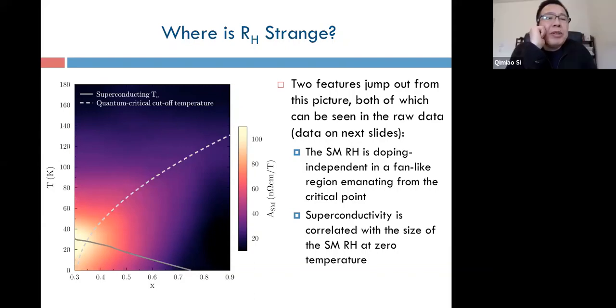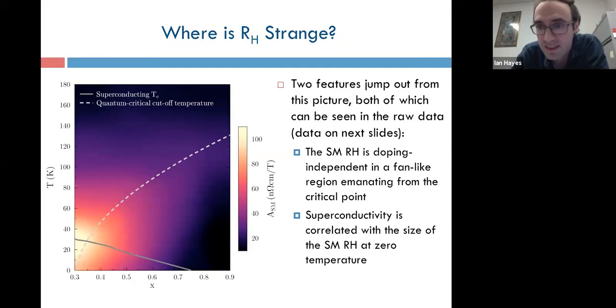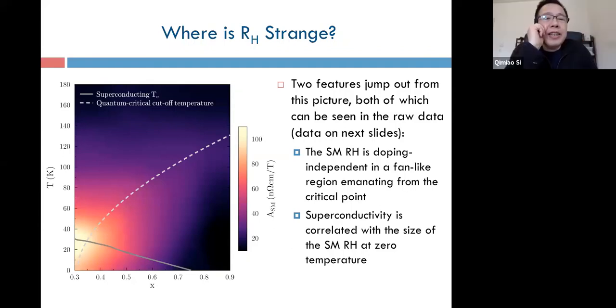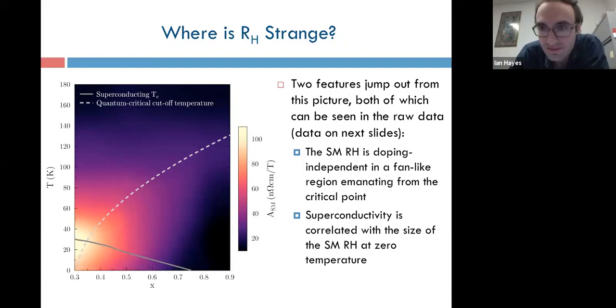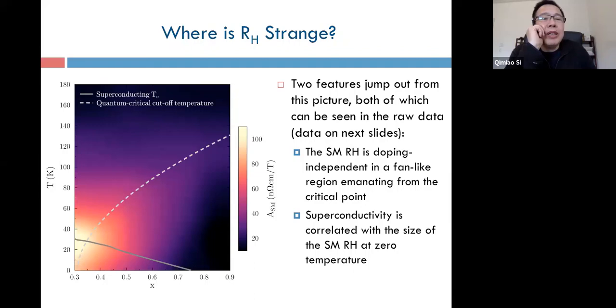Ian, do you mind if I interrupt you? Yeah, not at all. If I take the dashed line literally, it's somehow in deviation with my understanding of what happens in the phosphorus doped materials. In other words, the critical slowing down doesn't actually go all the way to 0, that even at around optimal doping, there seems to be various indications that there's some truncation. So the dashed line, in that sense, I would have thought that it doesn't really terminate at 0.